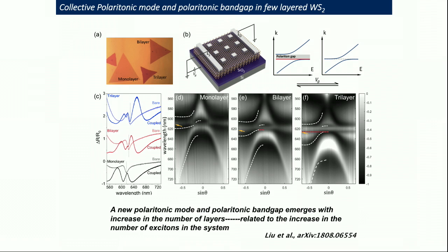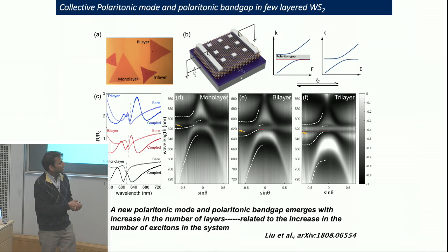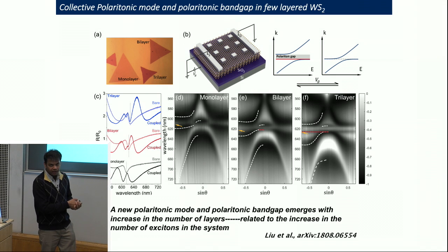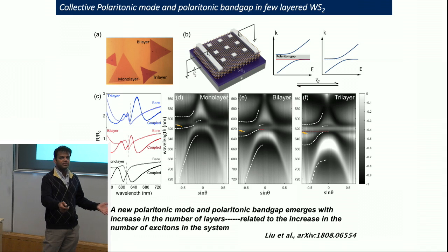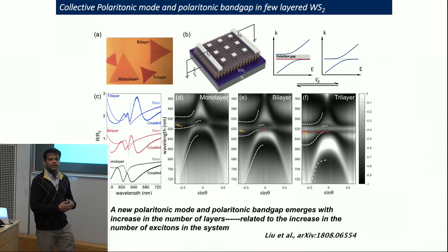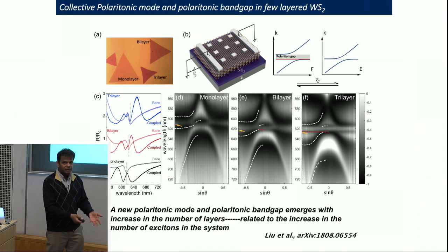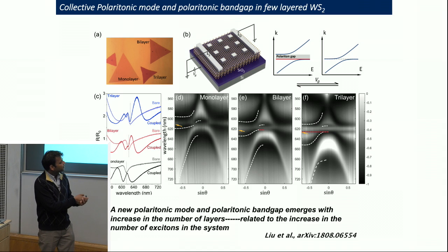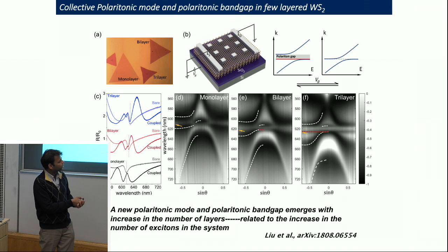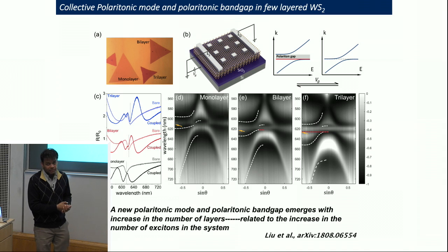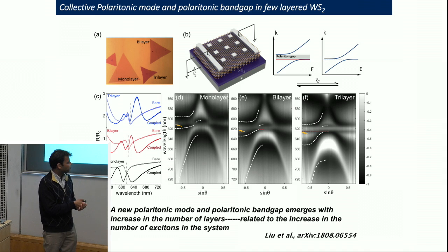This is bright, which basically means that there are no excitations allowed in the system. So we call this a band gap. What we create is a polaritonic band gap, because there are no excitations, just like in an electronic band gap region, there are no electronic excitations in the system. Same thing here. And then you have this upper polariton branch. So the question we asked was, what is the origin of this new mode that emerges in this system? And what is the origin of this polaritonic band gap?